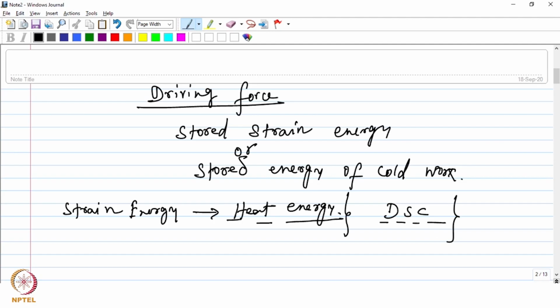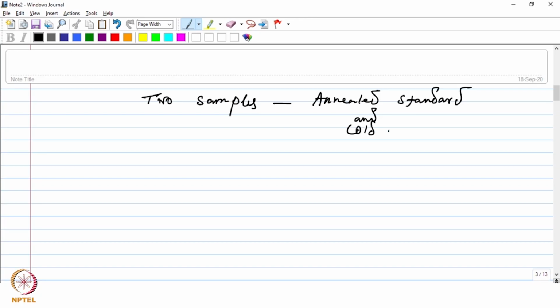Okay. And another way of looking at it, in physical terms, as to how exactly this strain energy comes out, and the way you can visualize it, is through two samples. One will be used as the standard, which is an annealed sample, and another is the cold worked sample of the same material. So you take these two samples in an instrument in which you can actually measure the power which is required to heat these materials to a particular temperature. So you can actually see the difference of power which is required to heat the standard sample and the cold worked sample to a particular temperature.